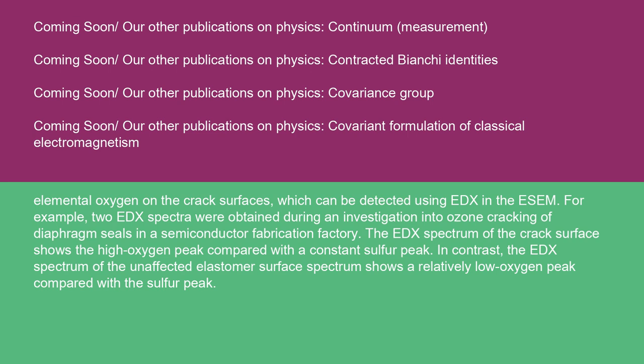For example, two EDX spectra were obtained during an investigation into ozone cracking of diaphragm seals in a semiconductor fabrication factory. The EDX spectrum of the crack surface shows a high oxygen peak compared with a constant sulfur peak. In contrast, the EDX spectrum of the unaffected elastomer surface shows a relatively low oxygen peak compared with the sulfur peak.